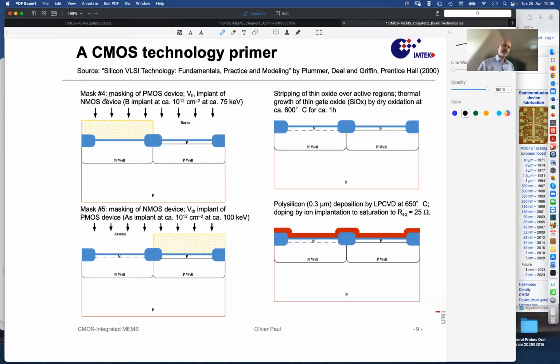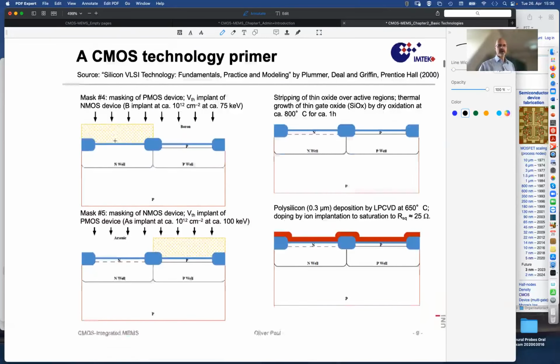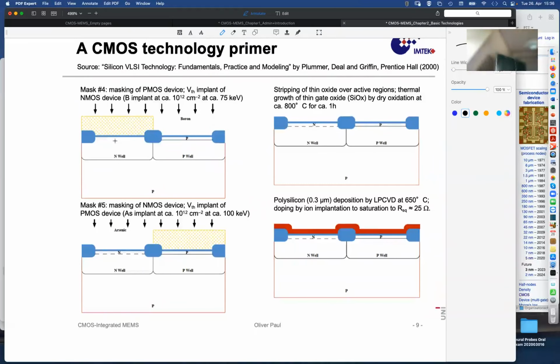And also note that now we already have used 5 masks, back and forth. Well, actually, we kind of use the same mask again, for this left and right protection. This has happened now several times. So we did not use different designs maybe, but we have done lithography many times. And repeating technologies over and over again increases always the chance to do something wrong. The overall rate of failure is a product of individual rates of failure. So the more complicated technologies are, the better controlled the individual steps must be, so that at the end something useful comes out.